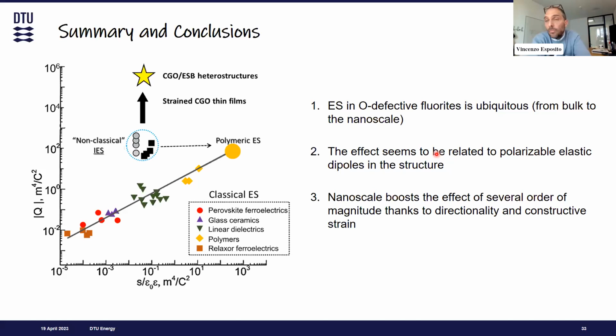What we are seeing here is completely still, because we are at room temperature, where the thermal energy is very, very low, and the mobility of the vacancies is also very low. The same we can say for the other electronic defects that we usually see in these materials at high temperature. That said, I have to say that defects usually bring defects. So if you have an oxygen vacancy, it is possible to generate other electronic defects, especially if you apply pretty high electric fields. So there can be some electronic conduction, but this seems not to harm the electromechanical properties too much, and somehow can even help in some cases.